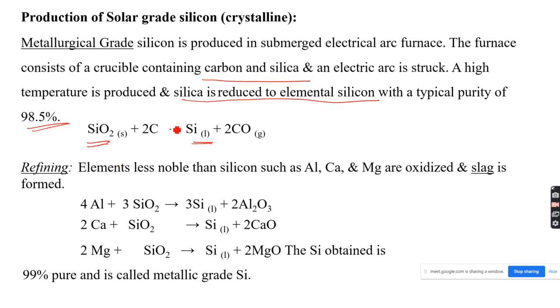So silica, SiO2, in the presence of carbon is reduced to elemental silicon. And further, this elemental silicon contains some impurities such as aluminum, calcium, and magnesium. Elements less noble than silicon, such as aluminum, calcium, and magnesium, are oxidized and slag is formed. That is, when you heat silicon to a very high temperature, the aluminum interacts with the silica, forming free silicon. Again, it is solar grade silicon along with the oxides of aluminum, calcium, and magnesium. The silicon obtained is now 99% pure, which is again called metallurgical grade silicon.